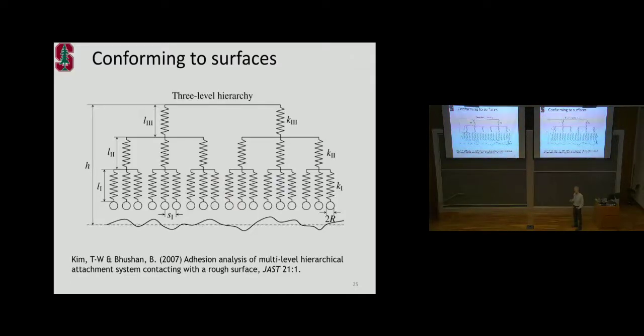And a way to think about that goes back to the selective compliance idea at the very beginning of the talk. If you just have compliance, that also will not get you there. There was a paper by Bharat Bhushan where you look at what is an optimal array of compliant elements for an adhesive, which you can model as a hierarchy of springs. Okay, so this is good for conforming to the surface, but it won't improve your adhesion. And the reason why is you can just imagine what happens if I take that surface and push it down. Some of these elements are going to hit the bumps first, and then you have to keep pushing a bit further before these ones make contact with the valley.